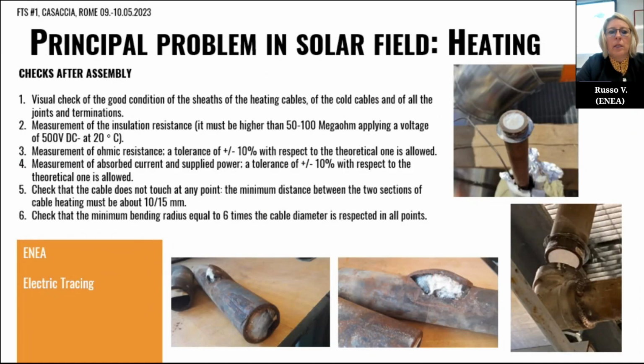As a best practice, after installing the cable, it would be good to carry out some checks, for example a visual check of the good condition of the sheath, or some measurements. For example, we can measure the insulation resistance, the absorbed current or the power supply. Then we also have to check that the cable doesn't touch at any point. In fact, the minimum distance between two sections of the heating cable must be around 10-15 millimeters. And finally, we have to check the minimum bending radius, which has to be equal to 6 times the cable diameter.